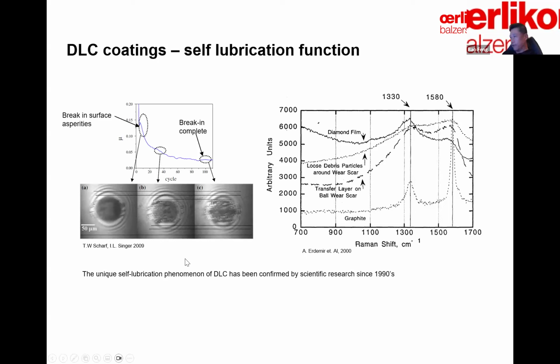But the difference with DLC is that DLC will last. It has a high wear resistance, and it will provide low friction at the same time. It will last for a long time, as opposed to the other solid lubricants I've talked about. Those coatings only provide the benefit at the very beginning of the contact, then get wiped off in a short time. This study has been repeated by hundreds of researchers from different research groups, and the graphitization phenomenon is real. It has been confirmed over and over.